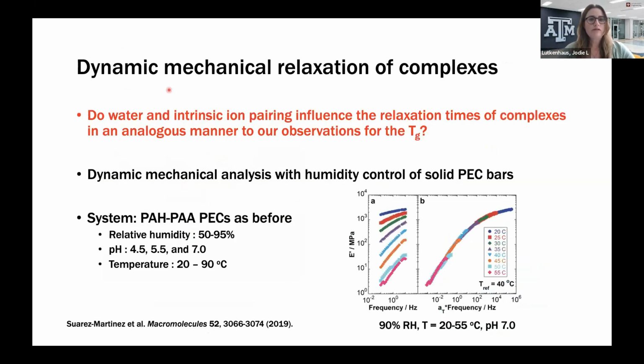Let me move forward to dynamic mechanical relaxation of complexes. So next, I want to go through this idea of the polyelectrolyte relaxing in the complex. If you go through a glass transition, there's a relaxation. You can also see a relaxation using dynamic mechanical analysis, which is a method that holds your polyelectrolyte complex film and applies a sinusoidal tension, and you can look at the in-phase and out-of-phase responses.